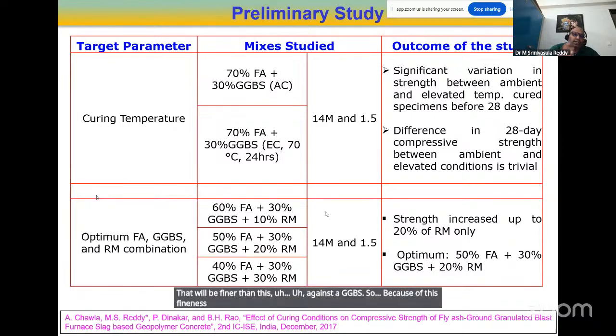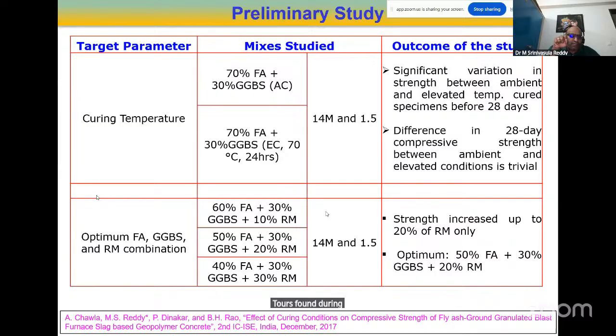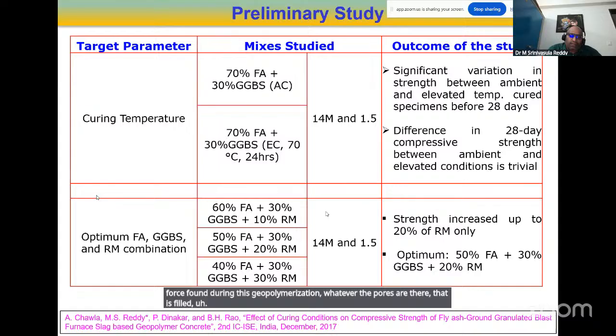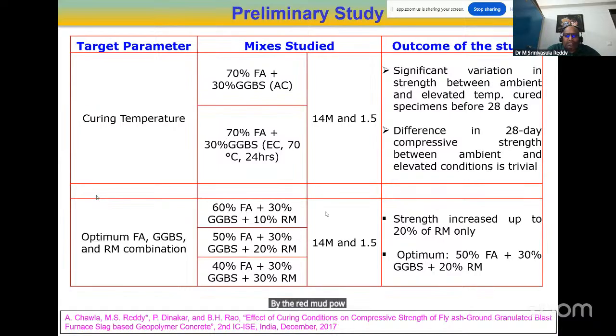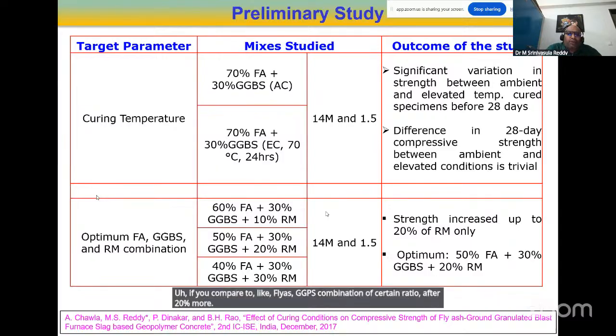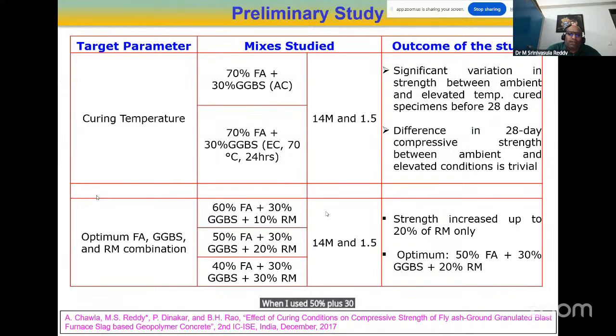Because of this fineness, it has entered into the pores formed during geopolymerization. Whatever pores are there are filled by the red mud powder. Because of this, I observed, compared to a fly ash GGBS combination at a certain ratio, 20% more when I used 50% fly ash plus 30% GGBS plus 20% red mud.